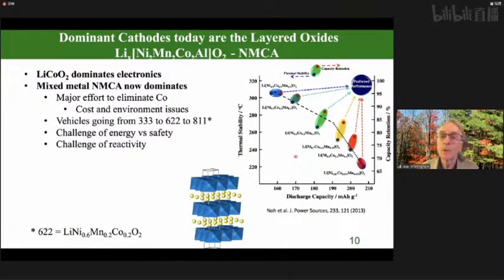What we have here is a plot of the thermal stability versus the discharge capacity for a range of these mixed metal oxides. That's nickel, manganese, cobalt, aluminum, what we call NMCA, and the formula is given at the bottom here. And you'll see the nomenclature like 622 just means 60% nickel, 20% manganese, 20% cobalt. So you'll notice on here, if we want the highest thermal stability, we have the lowest discharge capacity. If we want a high discharge capacity, then we have low thermal stability.